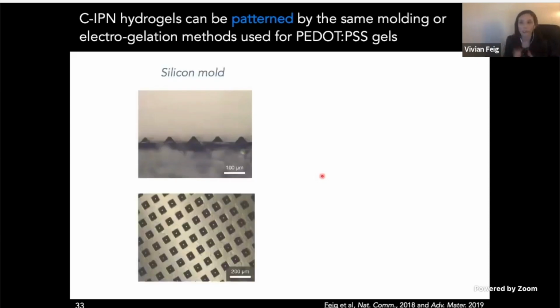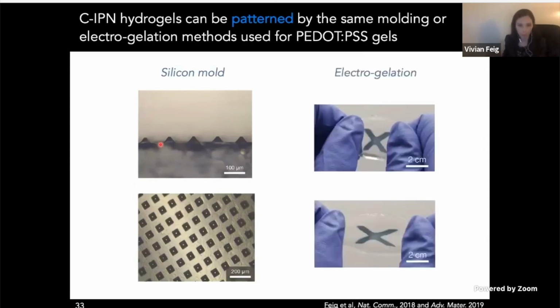And finally, we can pattern these CIPN gels using the same methods described previously, where with the ionic liquid, we can mold them into different shapes, like these micropyramids that were made with a silicon wafer mold. And after you have the molded conductive network, you can backfill them with monomers and polymerize them in this very same way to make these stretchable gels. But we can just as easily increase the complexity of what we can make by using electrogelation, where, for instance, we can pattern this X shape and then backfill them with monomers. And if we polymerize it together with the bath, then not only do we have this stretchable conductive pattern, but we have something that's also intimately integrated with that stretchable hydrogel substrate underneath.